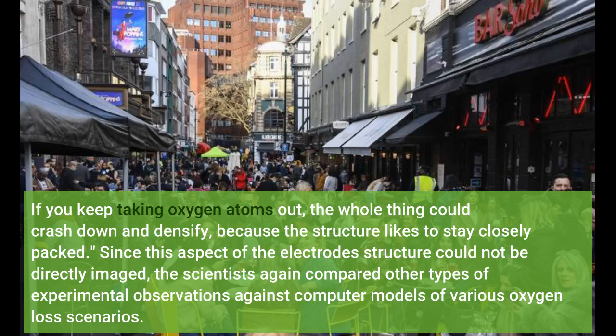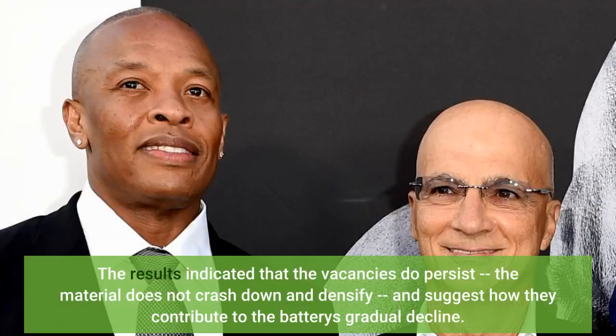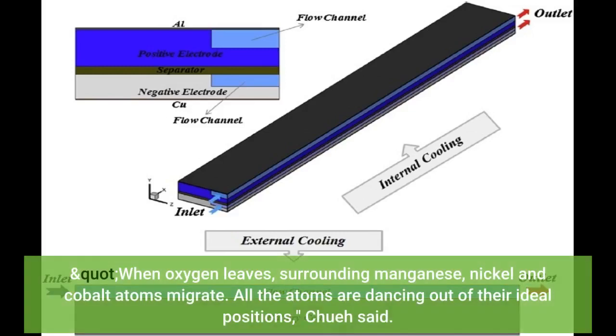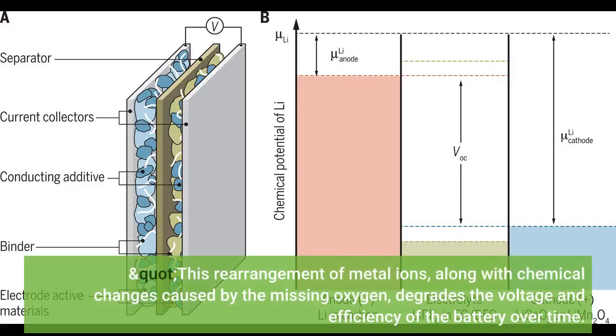Since this aspect of the electrode structure could not be directly imaged, the scientists again compared other types of experimental observations against computer models. The results indicated that the vacancies do persist. The material does not crash down and densify, and suggest how they contribute to the battery's gradual decline. When oxygen leaves, surrounding manganese, nickel and cobalt atoms migrate. "All the atoms are dancing out of their ideal positions," Chueh said. This rearrangement of metal ions, along with chemical changes caused by the missing oxygen, degrades the voltage and efficiency of the battery over time.